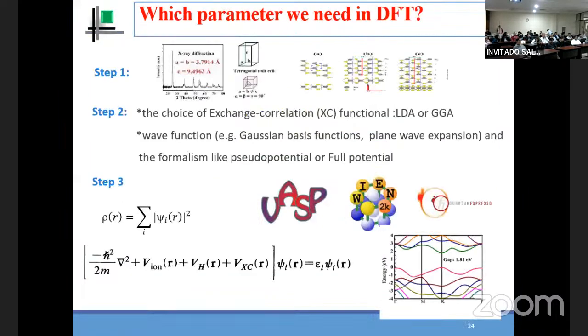So the first step for applying DFT, we need some parameters like lattice parameter, crystal structure, and atomic positions of the system. So we can choose the good exchange correlation functional, which one we can use for any calculation, and the basis for the wave function. It's like Gaussian or plane wave expansion, and the formalism for this approach. I don't know if some people here use DFT, because we have many codes applying DFT, but the most used codes, as we can see here, are Quantum Espresso and VASP.